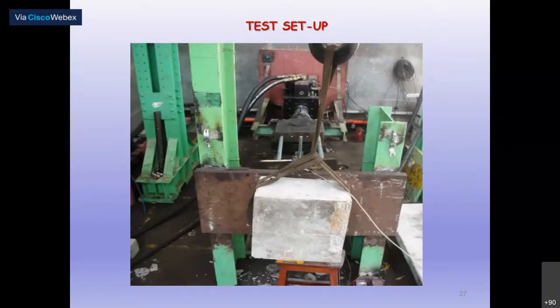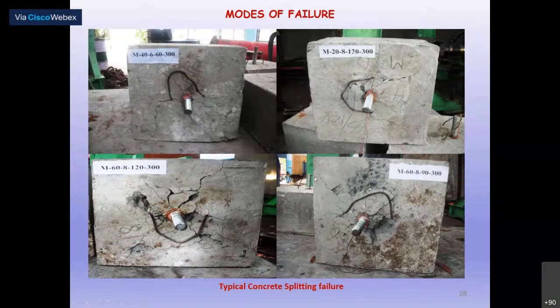So then we tested this again. After seeing the facilities available, we could have this setup. Then we tested them. Finally, the understanding of the precast elements with the different reinforcement detailing, with the different materials involved, we can find out. So we need to develop a material or precast element which will exhibit good ductility and good strength, but avoid sudden failures. In this process, a lot of parameters are involved and varied. Then they tested in the laboratory. We found that many parameters like strength and capacity are improving.